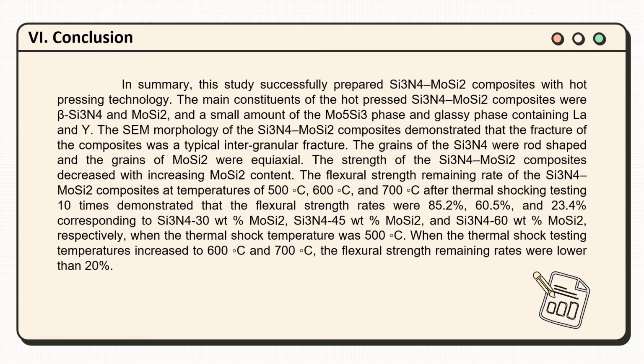The flexural strength remaining rate of the silicon nitride molybdenum disilicide composites at temperatures of 500 degrees Celsius, 600 degrees Celsius, and 700 degrees Celsius after thermal shock testing 10 times demonstrated that the flexural strength rates were 85.2%, 60.5%, and 23.4%, corresponding to the silicon nitride with 30 weight percentage of molybdenum disilicide, silicon nitride with 45 weight percentage of molybdenum disilicide, and silicon nitride with 60 weight percentage of molybdenum disilicide respectively, when the thermal shock temperature was 500 degrees Celsius. When the thermal shock testing temperature increased to 600 degrees Celsius and 700 degrees Celsius, the flexural strength remaining rates were lower than 20%.